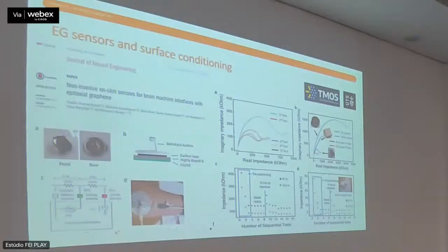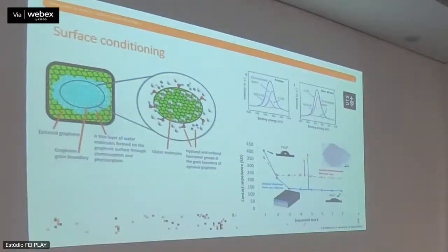And they are particularly extremely stable in saline solution. As you know, in sweat, there's a lot of salts present on the skin, and a lot of metals can corrode, for example, or composites can start to delaminate. This does not happen in this system. Graphene is very resilient, and the adhesion is high enough to maintain very good reliability. And actually what is happening, which does not happen if you have large plates of graphene, is that you can make this graphene go from hydrophobic, so completely hydrophobic, to quite hydrophilic over time, just by keeping it in contact with the moisture of your skin. And this is exactly what happens.